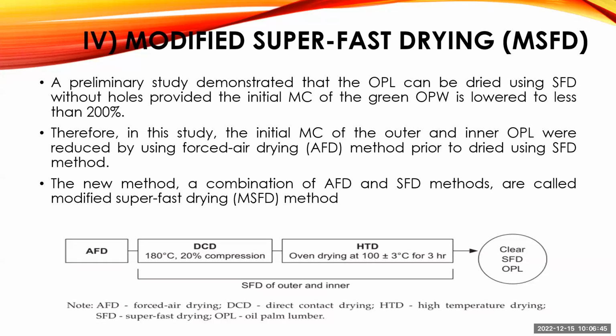Using this method, we combine forced air drying with the industrial fan to reduce the oil palm lumber moisture to a certain level, then use the superfast drying method - direct contact drying with a hot press, then put it in the oven for high temperature drying. Using this method we produce a clear surface of superfast dried oil palm lumber. This is good for us because we can use it directly during the lamination process, since the surface is without holes, clear, and looks very clean.